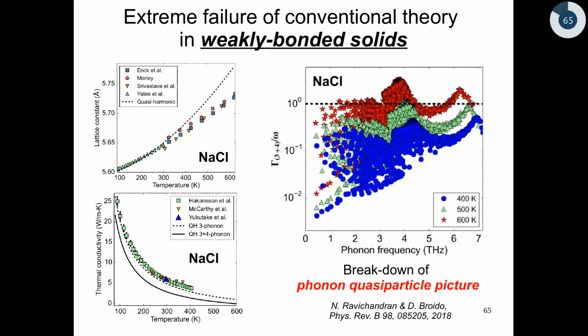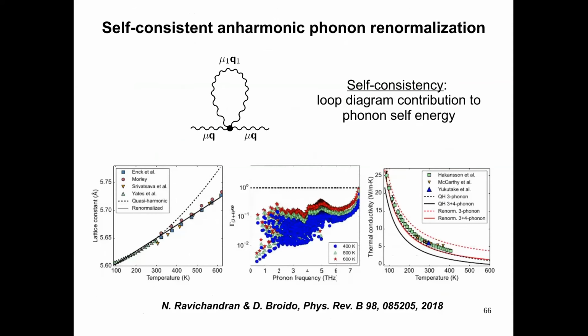And we found out, interestingly, that this failure of the conventional theory on thermodynamics is more fundamental in the sense that the phonon quasi-particle picture is itself breaking down. So for a phonon quasi-particle picture to work, gamma over omega should be much smaller than 1, gamma being the scattering rate and omega being the frequency. You can see that around 500 Kelvin, this assumption is broken down. So we developed a self-consistent renormalization theory framework to fix this issue. This renormalization scheme was based on this loop diagram that I think you're all familiar with.